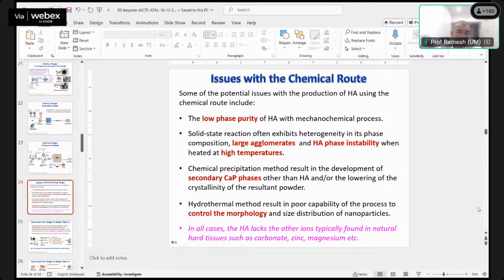Instability of the hydroxyapatite itself. Like just now, you saw different structures. Some look like a star, some look rod-like, some look like a spherical powder, that kind of thing. Normally, we find that the rod-like structure is more stable than the star-like, or in the form of a round circular particle. So the rod-like seems to be very stable. But again, depending on how you process them, you get different morphology, and that will influence the stability of the hydroxyapatite phase when you want to heat treat or when you subject it to sintering.